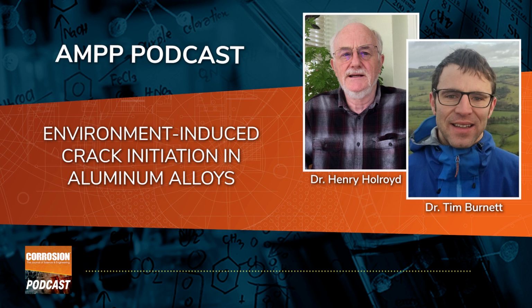But the issue is that the microstructure is on a scale of micrometers or even down to nanoscale features, and you've got meters and square meters, hundreds of square meters, maybe in an aircraft, where you actually have to resort to a more stochastic approach to predict initiation times and initiation locations, because you can't take into account that vast area of the material. So which are going to be the most likely locations? So we're forced to adopt a stochastic approach to have a practical way of predicting.